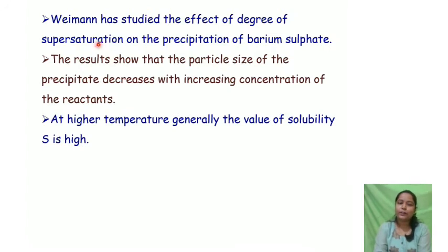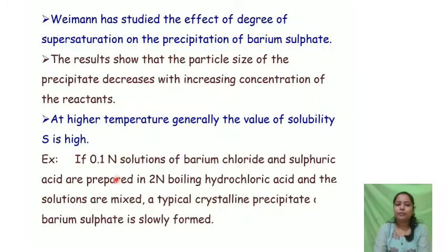Weimarn studied the effect of the degree of supersaturation on the precipitation of barium sulfate, and he observed that the particle size of the precipitate decreases with increasing concentration of the reactant, and also that at higher temperature the value of solubility is high. For example, if 0.1 normal solutions of barium chloride and sulfuric acid are prepared in 2 normal boiling HCl and then mixed, a typical crystalline precipitate of barium sulfate is slowly formed due to the supersaturation.